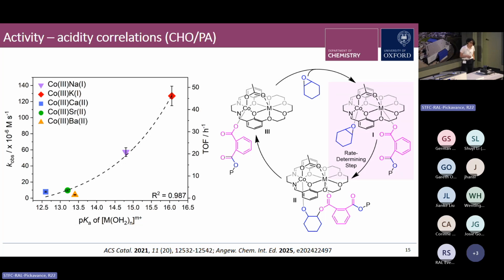intermediate, which is this metal carboxylate species, by the fact that the least Lewis acidic S-block metals, so sodium and potassium, most effectively labilize this metal carboxylate bond, which activates it towards ring opening of the epoxide, that then decreases your transition state barrier and increases catalytic activity with decreasing S-block metal Lewis acidity. Also from these results, we can gain some insight into the distinct roles of the metals in the polymerization mechanism by the fact that the least Lewis acidic S-block metals, so sodium and potassium, are most effective. It implies that the S-block metal does indeed bind the carboxylate nucleophile rather than the epoxide electrophile, because if the S-block metal was to bind the electrophile, we'd probably expect the most Lewis acidic S-block metals to perform the best.